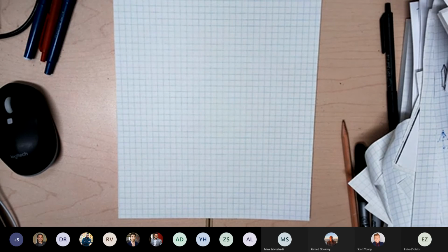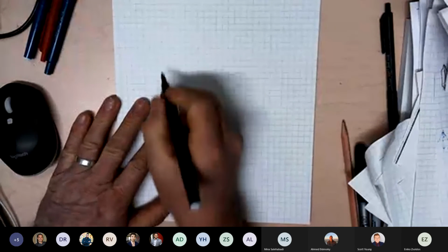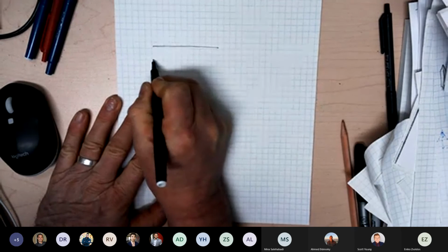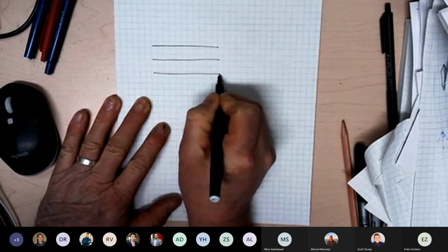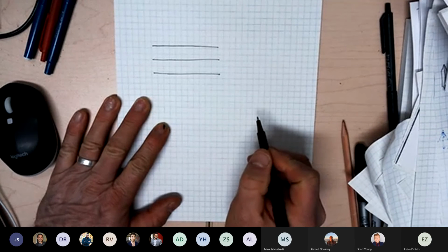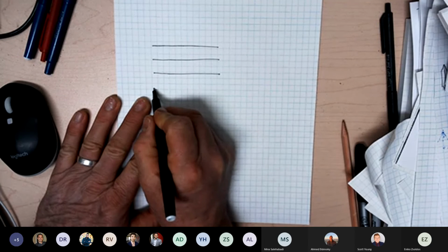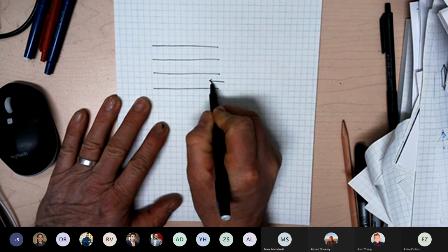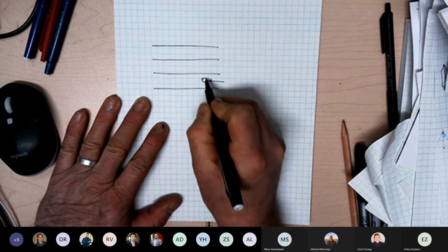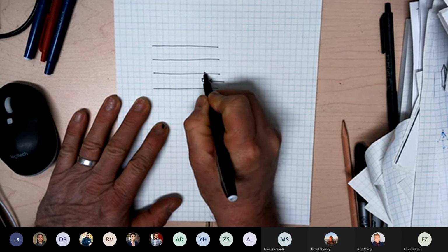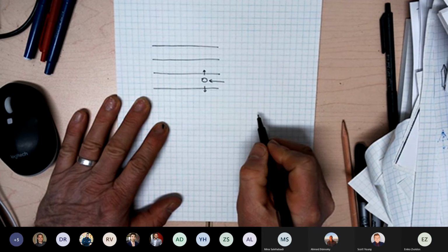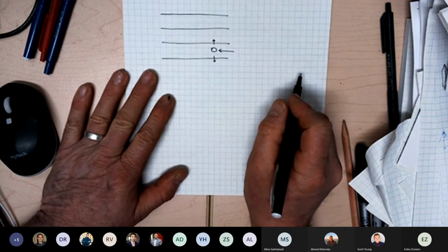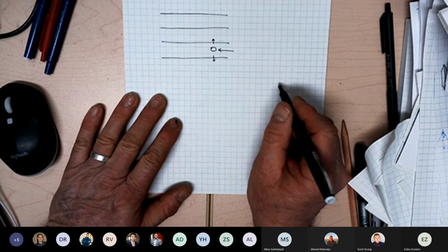So let's talk about where an attractive interaction may come from. Imagine you have a layered host like this. Every single layered host that exists, when you put the first intercalant atoms inside, the layers move apart just from the physical size of the intercalant. That's true for every single one. There are no layered systems that contract when you put intercalant inside.